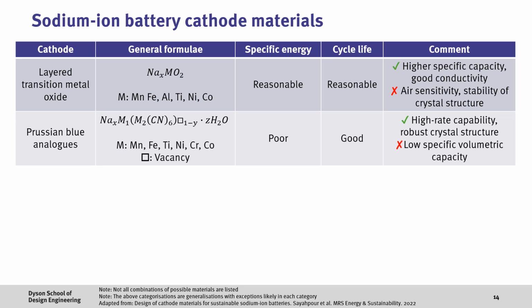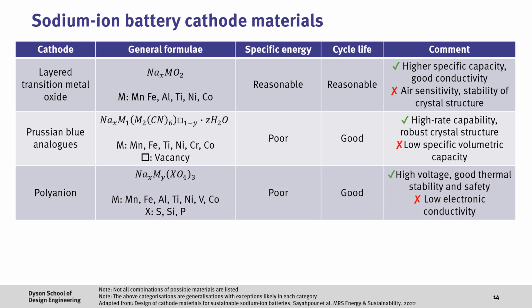Next, Prussian blue analogues have potentially good cycle life due to their robust crystal structure, which also enables high power capability. However, these materials generally have low specific capacity both volumetrically and gravimetrically. Finally, polyanion compounds can also have good cycle life due to a robust crystal structure, but again, low specific capacity. In addition to this, these materials generally have low electrical conductivity. However, they can have quite high voltages and good thermal stability, giving rise to better safety characteristics.